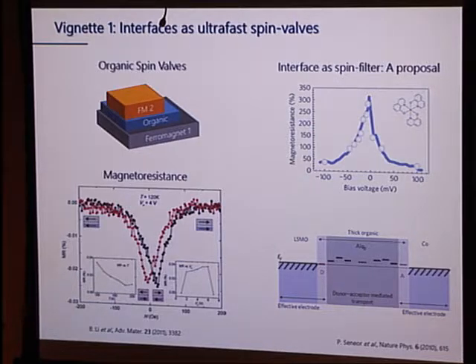Here's just one example. The idea is that you have the magnetization of the two electrodes parallel or anti-parallel, and as a function of that, there is a different resistance for currents to flow from one ferromagnet to the other. The realization often involves this molecule here, which is called Alq3, and one sees this bias voltage-dependent magnetoresistance. If you do it right, and at reasonably, not super low temperatures, but a little bit cold, you can get fairly large magnetoresistance. And there was a theoretical proposal that suggested that this was primarily driven by the interface between the organic and the ferromagnet, that there was something special going on there.